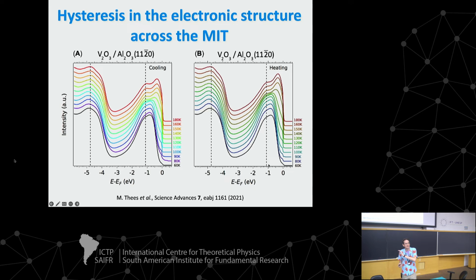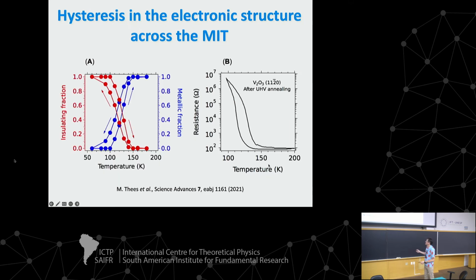three-peak model, one for the Mott-Hubbard band, one for the dispersive quasi-particle, and one for the quasi-localized state that is appearing in between. And then we can characterize the electronic hysteresis here.